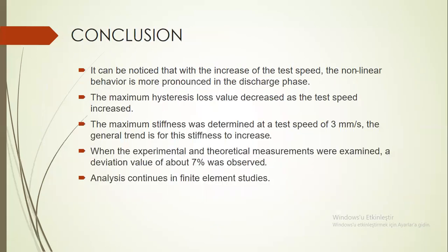It can be noticed that with the increase of the test speed, the nonlinear behavior is more pronounced in the discharge phase. The maximum hysteresis loss value decreased as the test speed increased. The maximum stiffness was determined at a test speed of 3 millimeters per second. The general trend is for this stiffness to increase. When the experimental and theoretical measurements were examined, a deviation value of about 7% was observed. Analysis continues in finite element studies.